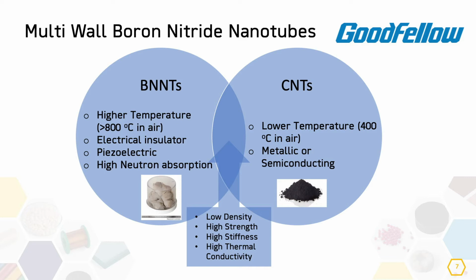So it is discussed and it has been claimed that boron nitride nanotubes will be the next generation material for the fourth industrial revolution. Why am I comparing them? Because boron nitride nanotubes and carbon nanotubes are more or less the same structurally. So they both have low density, they both have high strength and stiffness, and they both have high thermal conductivity. However, the boron nitride nanotubes, though they are structurally the same as carbon nanotubes, have boron and nitrogen atoms in their structure. Thus, they can also withstand higher temperature, and they are electrical insulators, because they have a band gap of 5.5 electron volts, while carbon nanotubes can be metallic or semiconducting, having a band gap of around 2 electron volts.